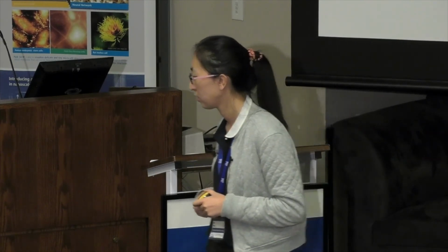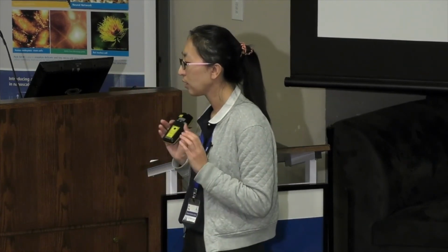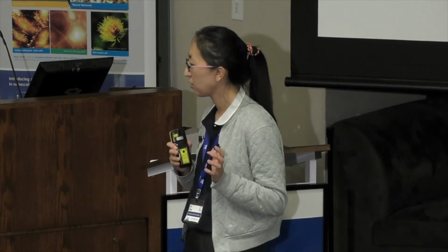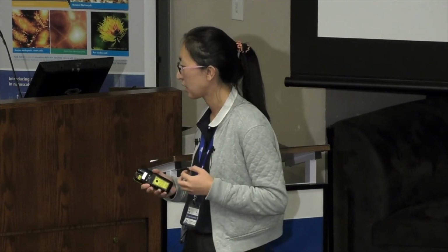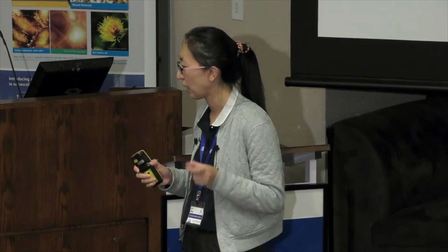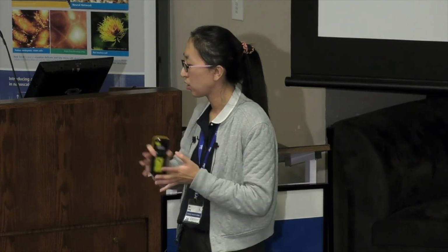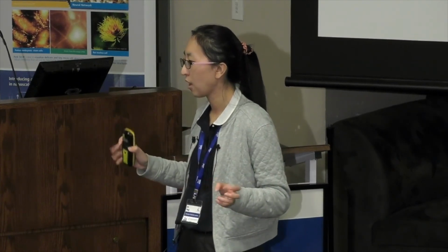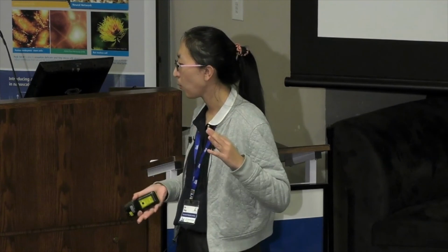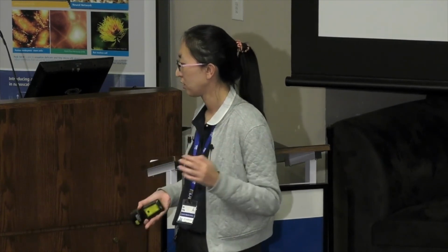So in general, the melting point is low, right? In general, it very much depends on the molecular weight of the polymer matrix. For the 4K sample, the temperature window is very small, at around 1.5 degrees C. But for the high molecular weight sample, we can control it because it has longer time for the polymer chain entanglement. So the time window and temperature window can be larger.